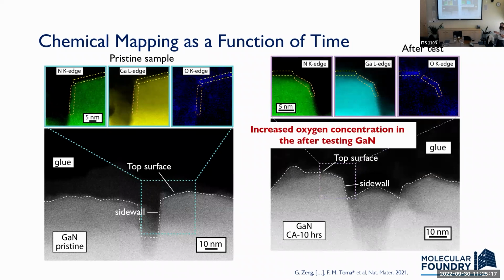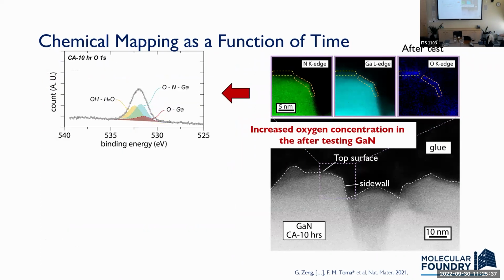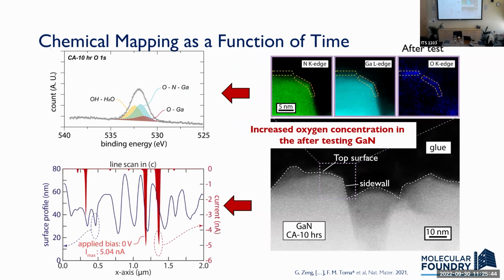Once we run our tests, what we observe is that still on the top surface, you don't have nitrogen, but you still have this component of gallium bound to oxygen. And then on the side wall, here is where something interesting is happening. You see nitrogen, you see gallium, you see oxygen. So you remember that XPS spectrum that I showed you earlier? This is the peak that we were observing, and it's related to the side wall. And it's also confirmed by the photoconductive atomic force analysis that I showed you earlier, where you see that the higher photocurrent is coming from the side walls.